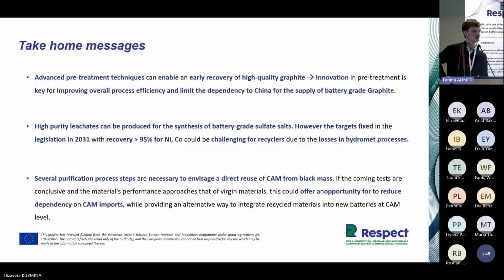Quick conclusion on the 3 messages that were mentioned in the presentation. So if we come back to graphite, we have shown within the first 2 years of the project that with innovation in pretreatment, we managed to separate graphite early in the process. The quality check is ongoing, but this is good news for Europe, and we could maybe try to promote a bit more this graphite recycling to limit our dependency to China for the supply of battery-grade graphite.